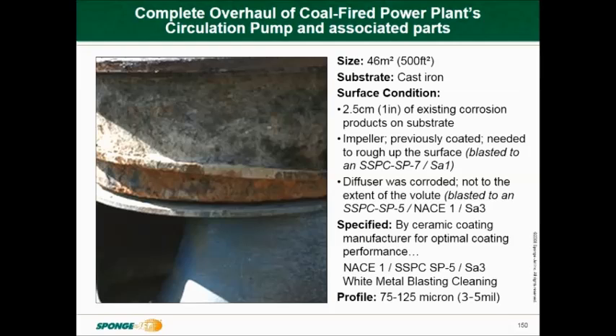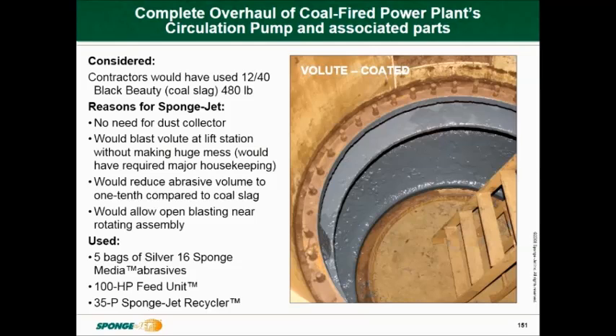The circulation pump square meterage totalled 46 square metres. It required a blast cleanliness level of an SA3, a near white blast, and the other parts only needed a whip up of the existing coating, I should say. Only 5 bags of Silver 16 were used in the blasting process, and that calculated to 90.5 kilos to abrade 46 square metres. That worked out as 1.967 kilos per square metre.